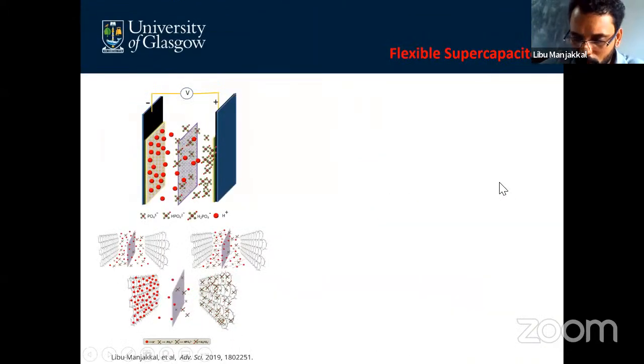But the major problem with this graphene foam based supercapacitor is that it has a limited energy density. I got nearly 3.4 microwatt hour per centimeter squared, so the application is limited. For example, for a chemiresistor sensor with low operating voltage or low current we can use that. But for a high power application, or to operate motors or actuators, I need more power. Then I started to prepare a new graphite polyurethane composite based supercapacitor. I prepared a new composite and developed a flexible supercapacitor on a graphene sheet and a flexible PET substrate.